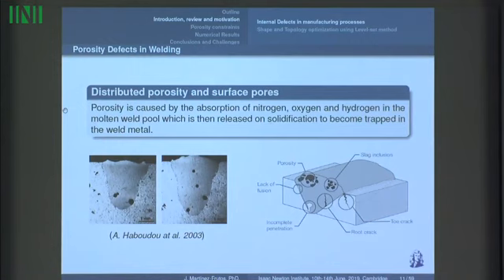Well, apart from casting manufacturing, porosity also appears in other manufacturing processes like welding. In welding, when the weld pool is melted, some gases get trapped as it solidifies. So we have this kind of defects that are small holes, and also we have other kinds of defects like incomplete penetration, root crack, and lack of fusion that can also be treated with the formulation I'm going to propose later on.